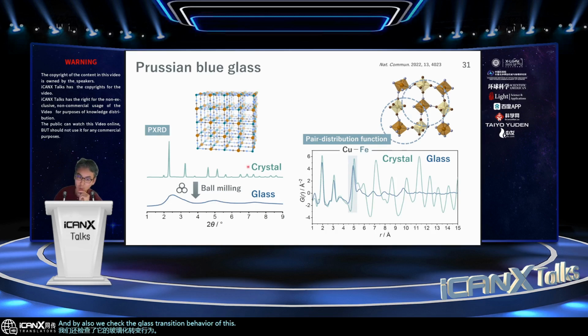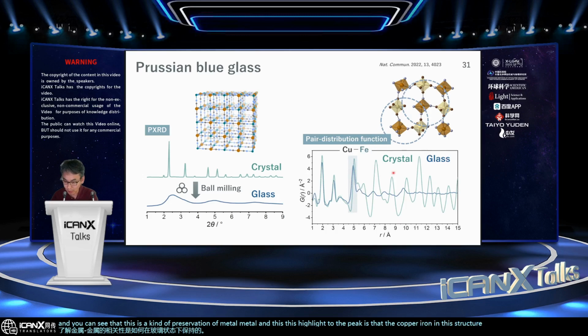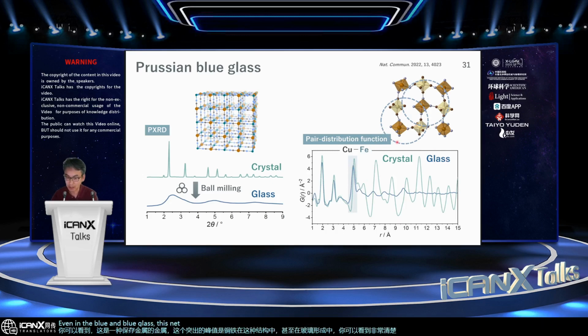Another interest is whether, even after forming the glass, this three-dimensional network is preserved or not. So we checked various characterizations, including the pair distribution function that I introduced, to understand how the metal-metal correlation is preserved in the glass state. And you can see this is a preservation of metal-metal. This highlighted peak is the copper-iron in this structure. Even in the glass formation, you can see a very clear peak, which suggests that even in the Prussian blue glass, this network structure is maintained.